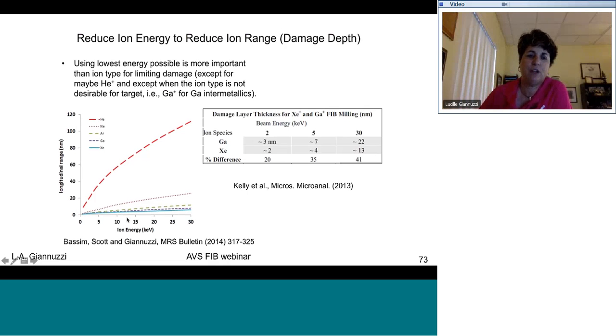So this is one of the graphs I showed earlier on, which shows that all these different ions, we take a look at the ion range, they all converge down to the really, really small value of about a nanometer or so, if you can get the ion energy low enough, okay? Helium is sort of this outlier. We're not going to talk about helium per se. And this graph here is perfectly shown by the experimental work here.